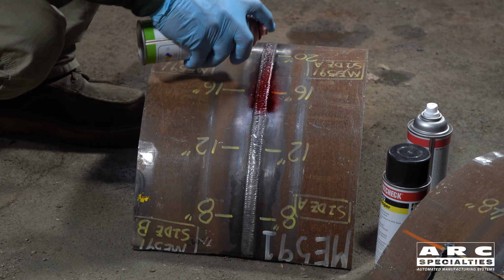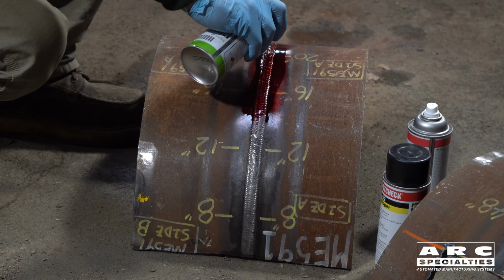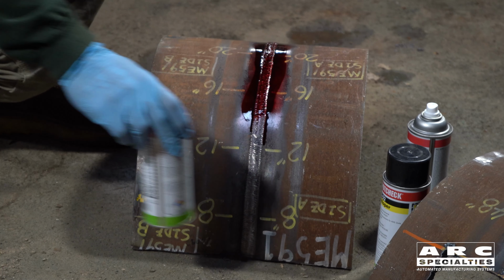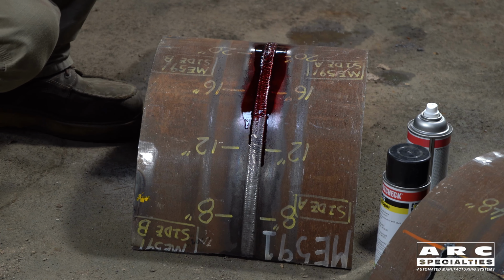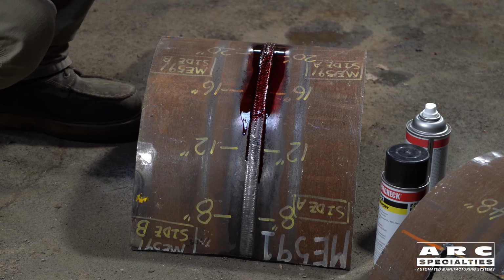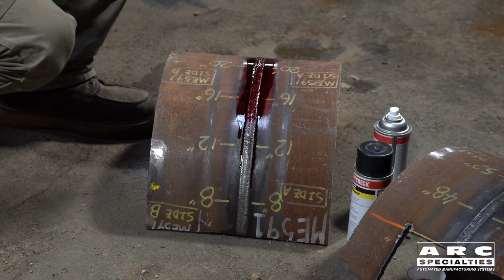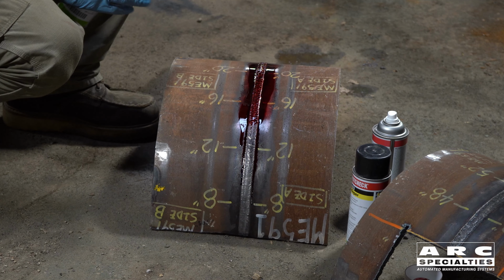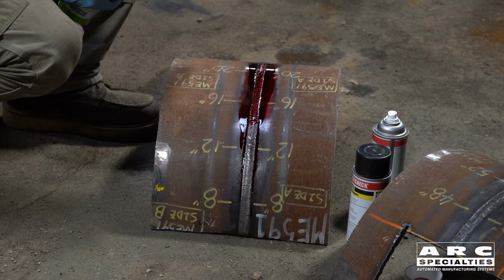So that penetrant's actually soaking into the defects? Yes, it will. The viscosity of the penetrant really dictates the length of your dwell time. And how long are we waiting on this one? This particular test here, we're going to wait 10 minutes according to our procedure.